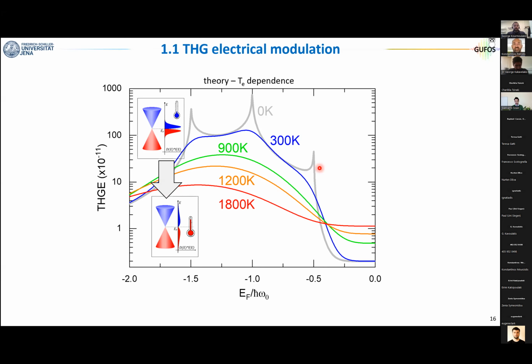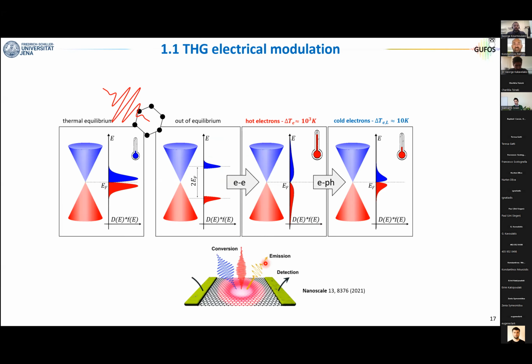And to understand why this is so relevant in nonlinear optics, we should also understand what hot electrons are and how they evolve. Now imagine that initially you have graphene at equilibrium, then you arrive with a very short pulse that breaks this equilibrium. At the very beginning, the system will be in a so-called out of equilibrium condition. That means you have delta Diracs in the upper and lower cone. This cannot be described by the Fermi-Dirac distribution. Next, you have electron-electron scattering, and this builds up the so-called hot electron distribution. So it's a situation where the electrons are described by the Fermi-Dirac statistics, but this time with a very high electronic temperature. And finally, by electron-phonon scattering, you relax, so you transfer the energy to the lattice, and electrons and lattice will have the same temperature.